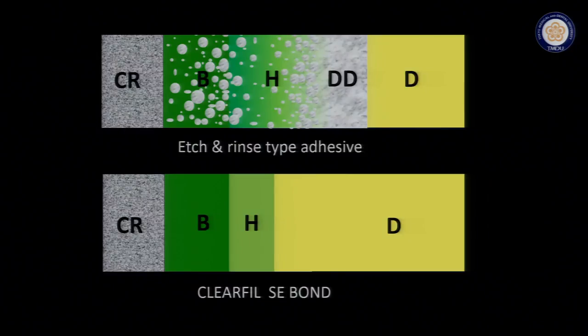I can show you the schematic diagram of the interface in case of etch and rinse type adhesive, especially in the case of wet bonding technique. We observe this kind of water and void at the interface. Of course, there are naked collagen layers at the bottom of the hybrid layer. In the case of two-step self-etching, there is no defect at this interface.